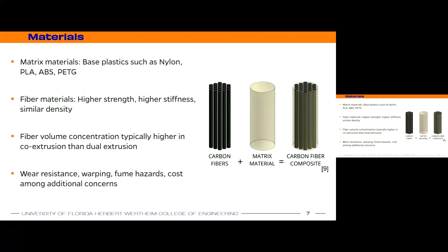And then this picture on the right is a little misleading because the fiber volume concentration is usually much lower than depicted, especially in the case of dual extrusion, because it requires what's called a pre-impregnation step, where the fiber bundles are held together by a resin made of the matrix material, and the resin can be as high as 80% of the volume concentration. And all that goes through one nozzle, while in the other nozzle in dual extrusion is pure matrix material. In co-extrusion, the pre-impregnation step isn't as prevalent, so there's usually a higher concentration of fiber in this case.